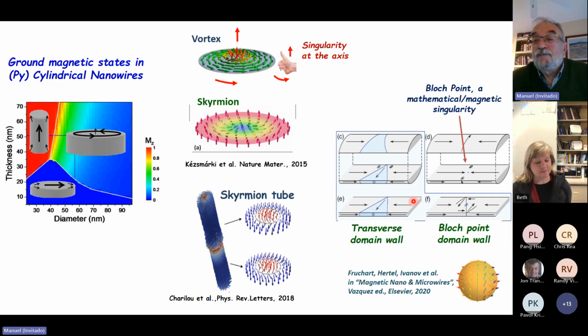Also, particularly for the case of cylindrical wires, the reversal of magnetization can be produced by transverse domain walls. That is similar to the two-dimensional thin films, but we can also have a Bloch point domain wall. This is a very metastable situation, and the Bloch point wants to be, like I mentioned before in the case of the microwires, in one of the ends of the nanowire in this case. So it moves very fast and produces the reversal of magnetization in many nanowires.